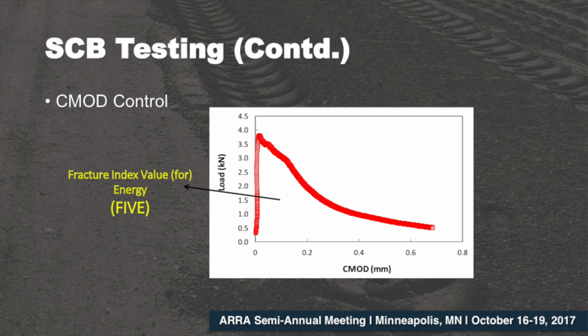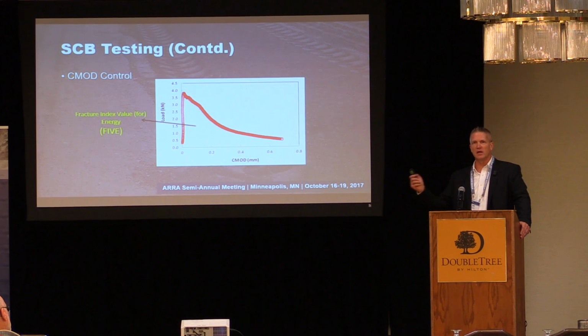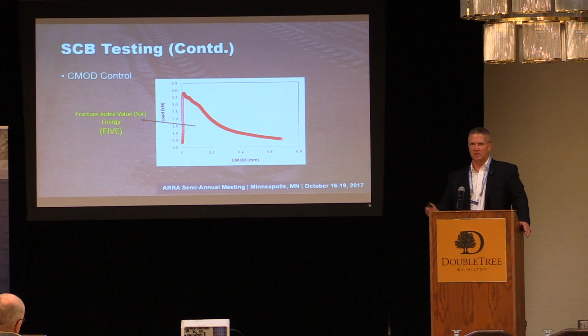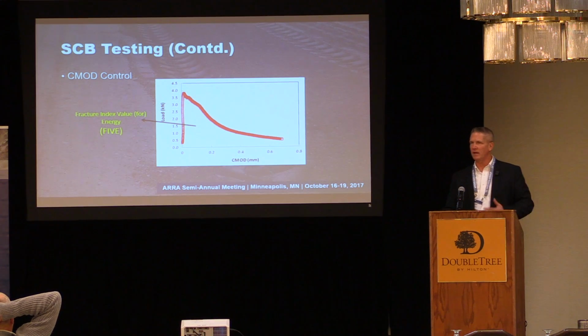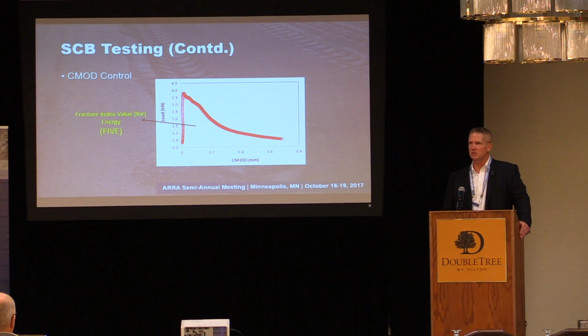And so when we went back and looked at a lot of the research, we found that a lot of people were having difficulty carrying out the fracture energy test to get the full tail of the sample. And so using the CMOD control, we were able to get that. But in reviewing with different folks in the industry and academia, even though your units are joules per meter squared, or a fracture energy value, it wasn't really following the accepted standard protocol, so we decided to call this value fracture index value for energy, or FIVE. And the whole point there being that we wanted to have a practical test that was going to be able to differentiate between materials that are used in the process and also be able to properly measure crack resistance and provide a test result that's certainly going to be reproducible and reliable in the field.